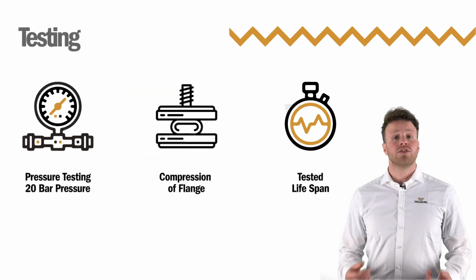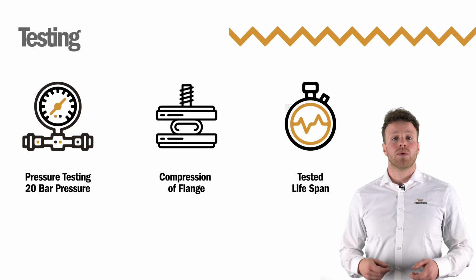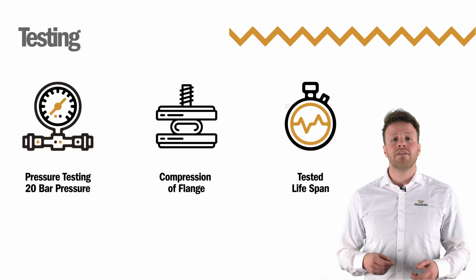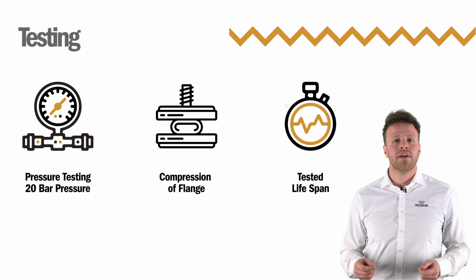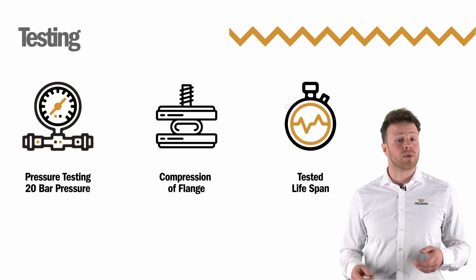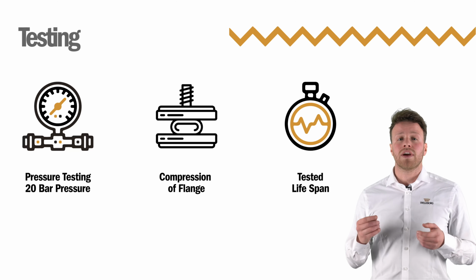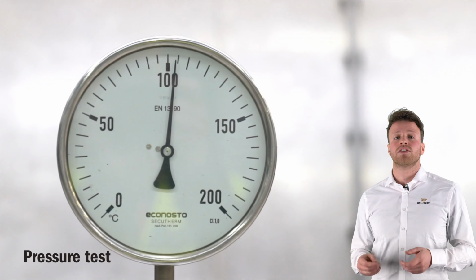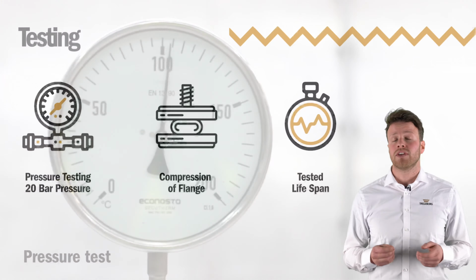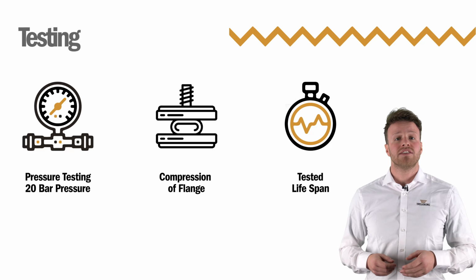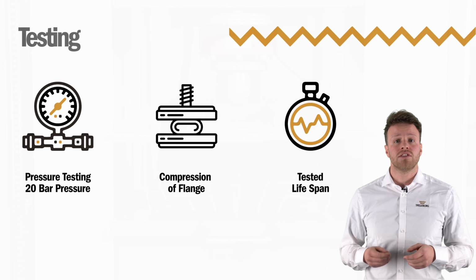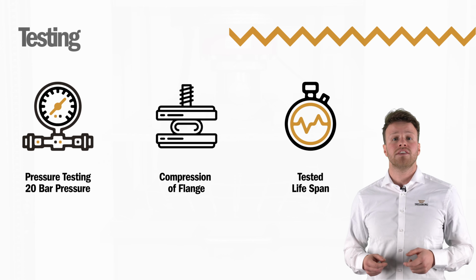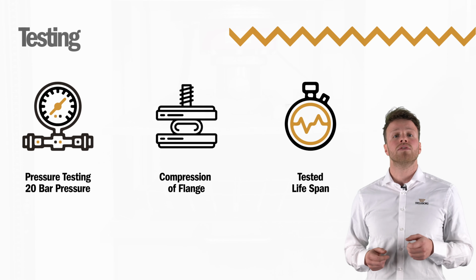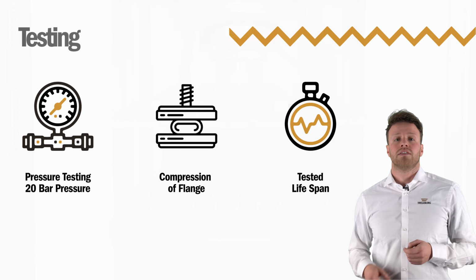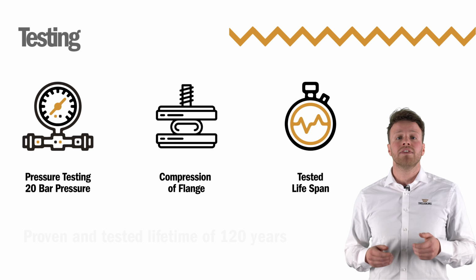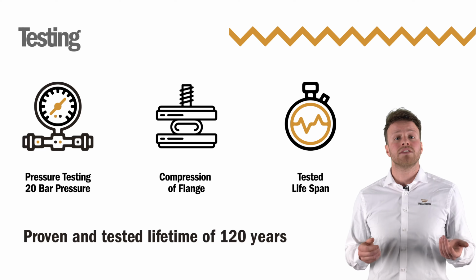endure. To ensure omega seals are of the required quality and that the material will behave as predicted over a long service life, they have to pass a series of minimal test requirements. To prove the strength of corner construction, we conduct pressure tests of up to 20 bar pressure. High relaxation makes the gasket fail over time, so we also perform compression of the flange to show it possesses low proven relaxation. The gaskets must also have a proven and tested lifetime of 120 years.